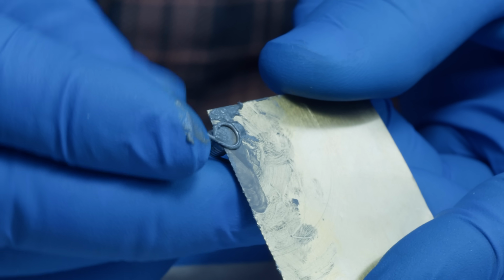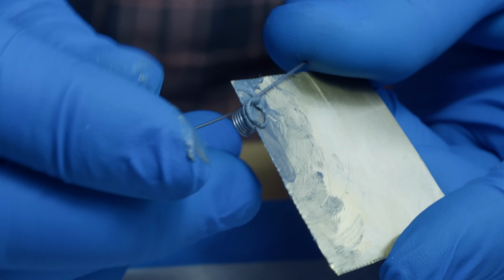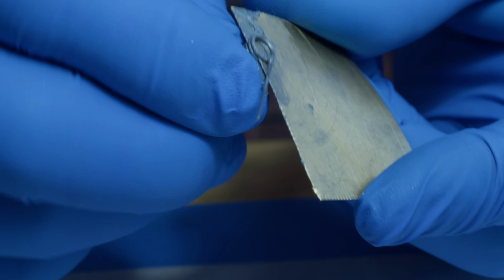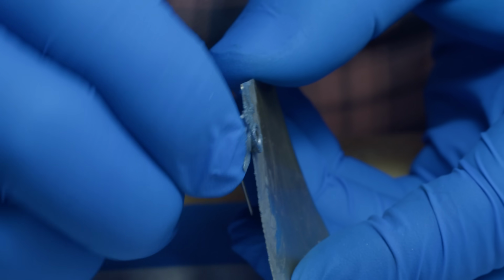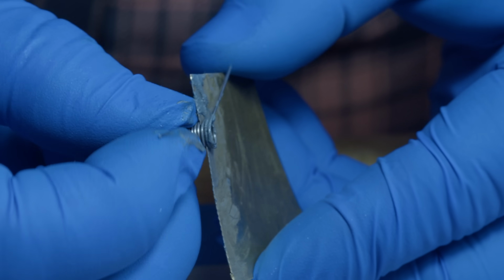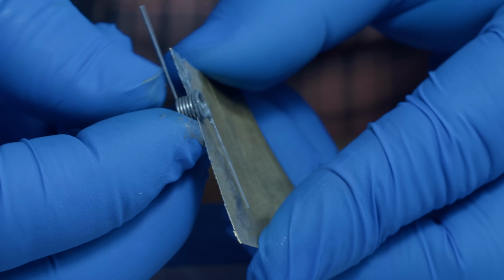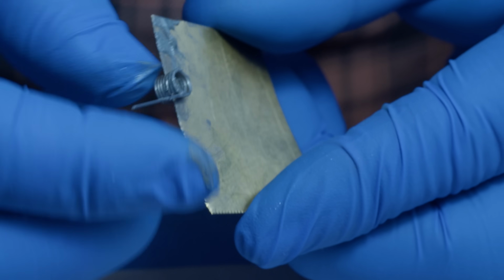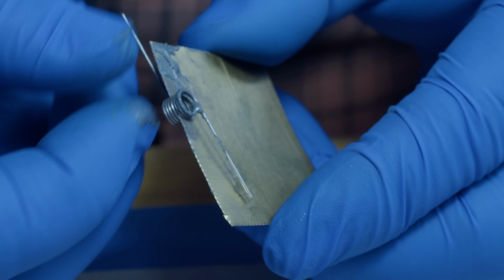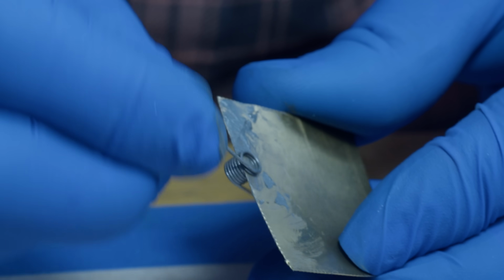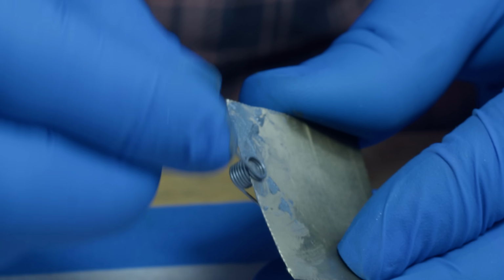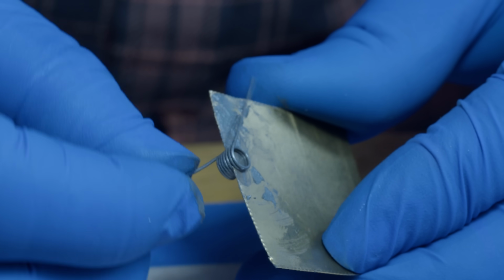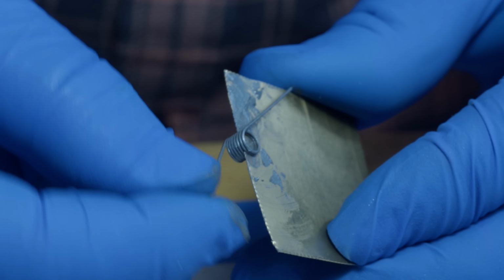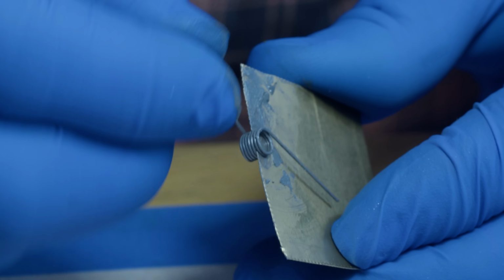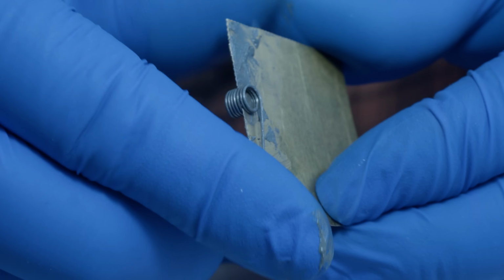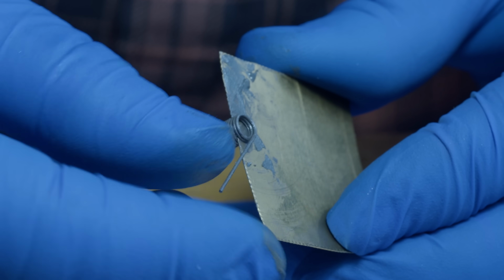and you put it on a thin piece of brass and run the brass and the polishing paste through the center of the torsion spring, you end up lapping the interface between the torsion coils to a much smoother profile, and it just gives a much nicer, smoother actuation. You don't have this gritty nature anymore. So this was a really good tip. I'm gonna start doing this for all torsion springs that matter, because it's really night and day difference between the feel of a polished and lapped spring versus one that you just get out of the bag.